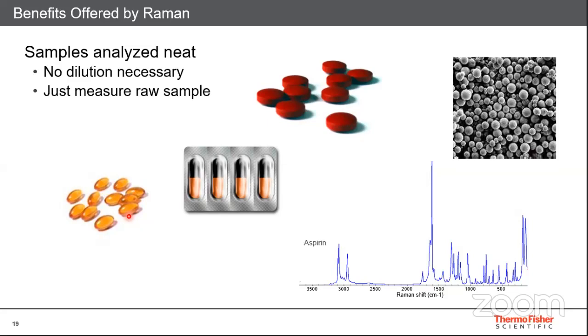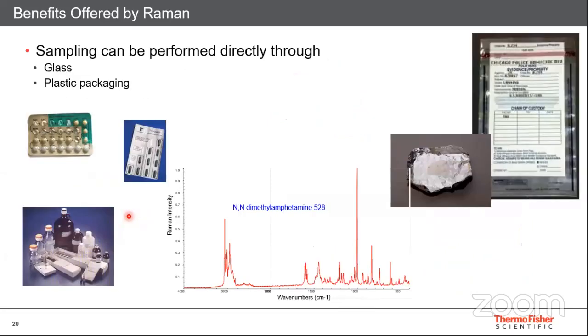Another important advantage of Raman is that the laser light can penetrate deeply, and you can have a confocal Raman spectrometer, and therefore, even if your sample is in glass or in plastic packaging, there's no problem. You just don't have to open it. Just do the analysis even through glass. Like, if you want to check what is there in the bottle, you keep the bottle and do the analysis of your sample. So this is the kind of advantage that Raman offers.